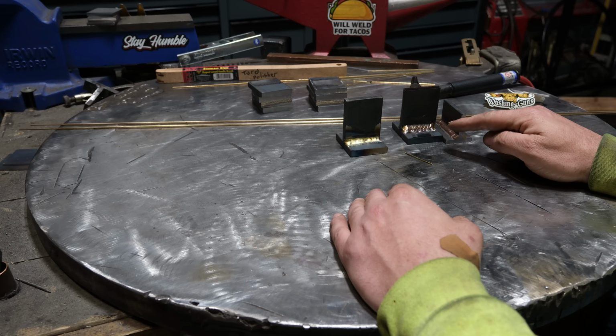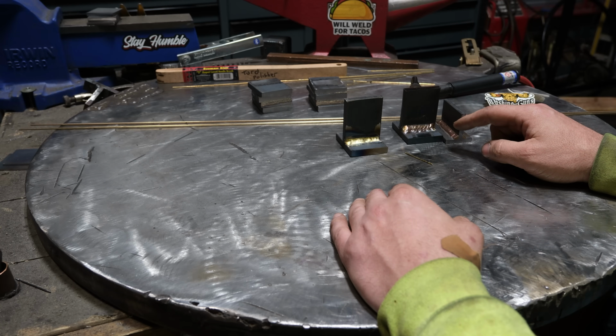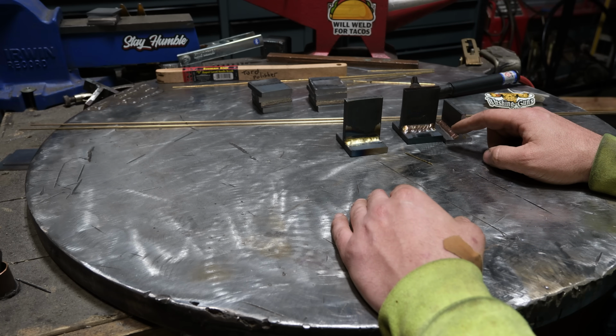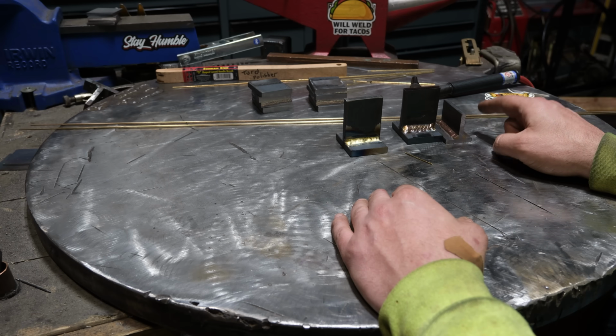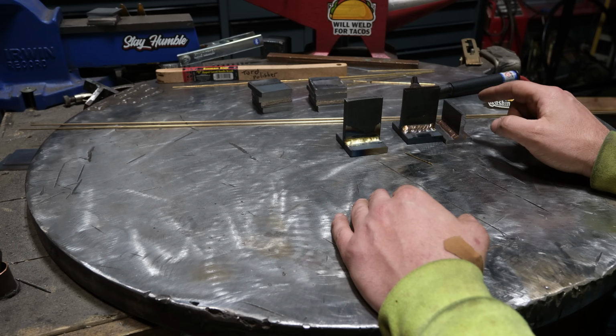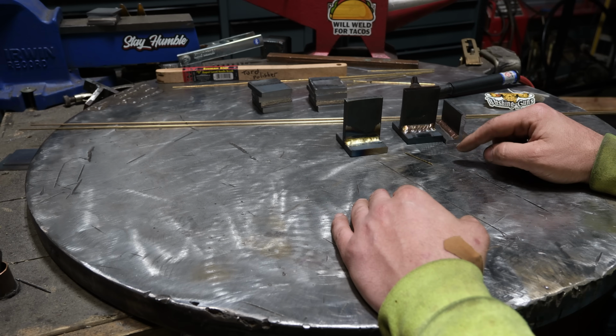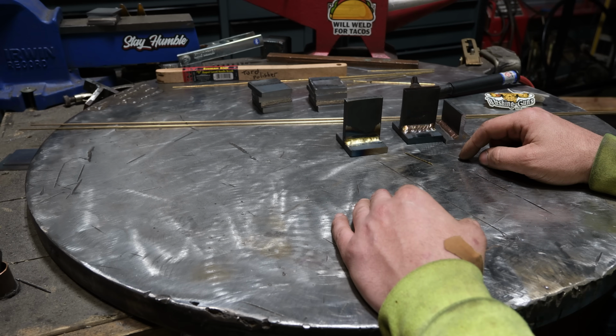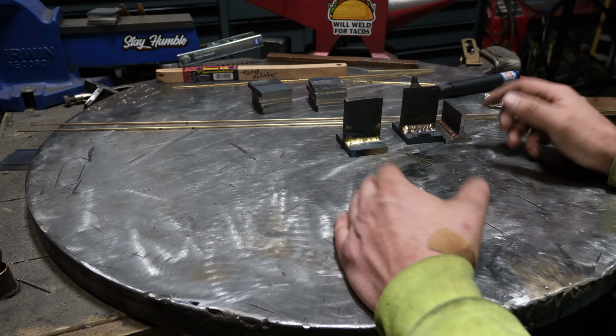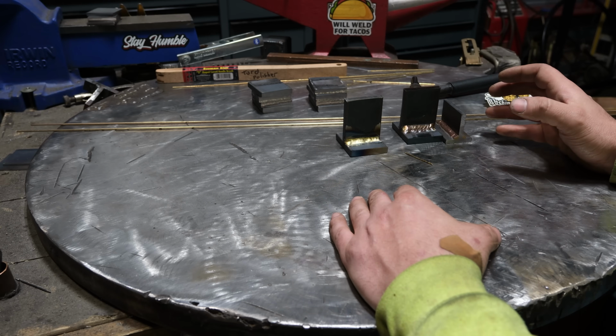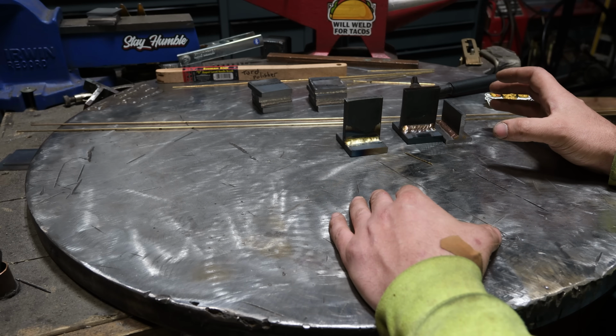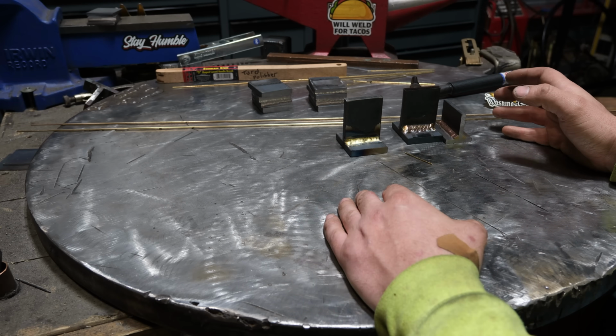I would suspect that on something like an exhaust manifold that gets ridiculously hot, aka close to the cylinder head, you may have issues where the welds crack, deform, or fail due to the high heat and temperature cycling, where this stuff will fail, but maybe a nickel rod or some other process wouldn't fail on you. It's something to think of.